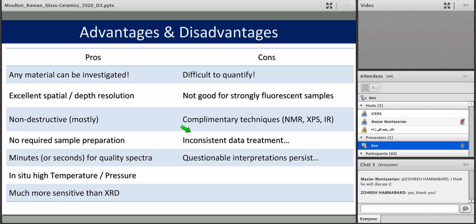The last two cons here, I'm going to talk a little bit more about, but there's quite inconsistent data treatment in the literature, and so to compare between studies, you have to apply the same data treatment that they applied, or you can't make a really rigorous comparison. And as a result of these inconsistencies in data treatments, the interpretations that are produced, even for the same system, are sometimes completely different. And I'll talk about this in more detail as we go.